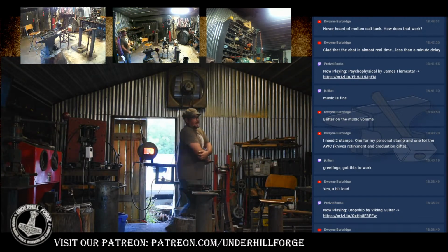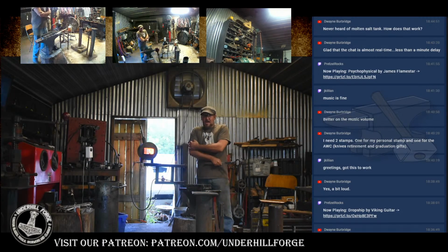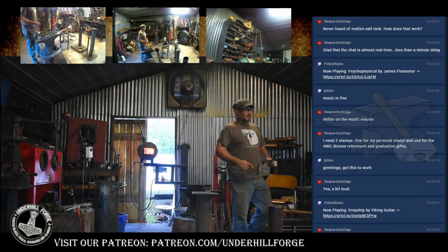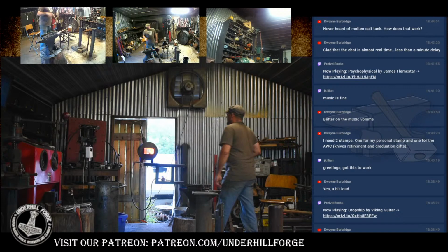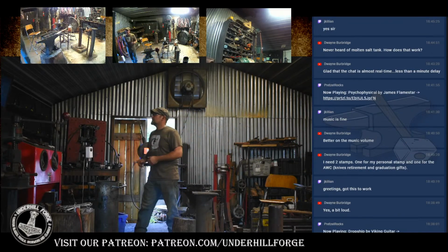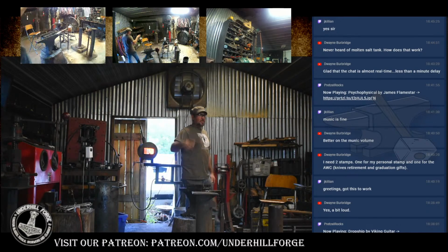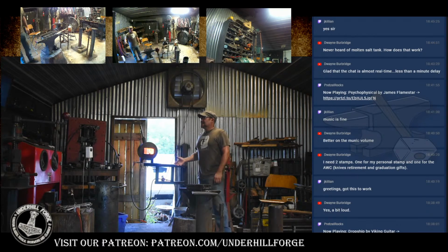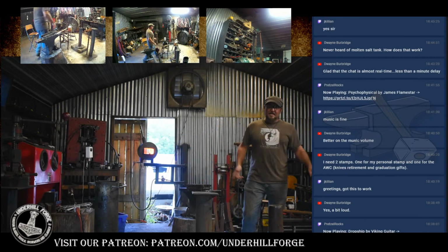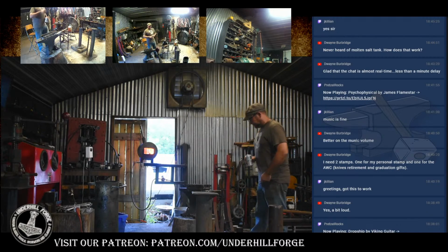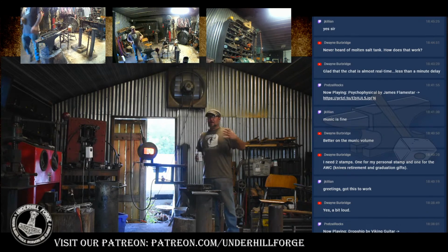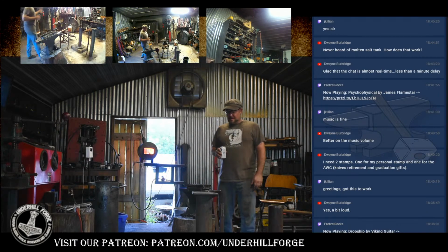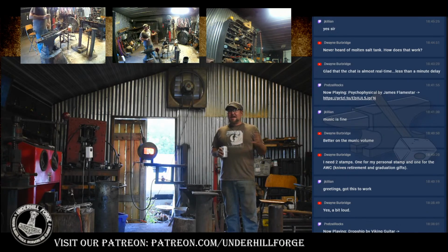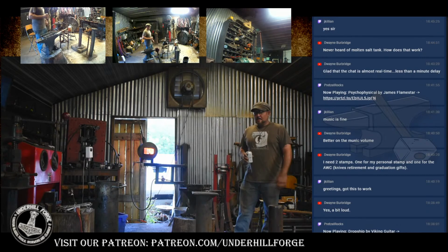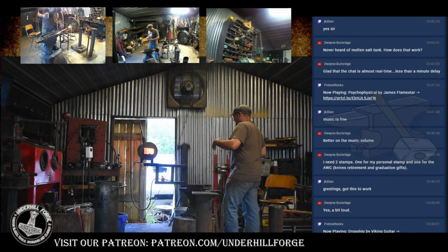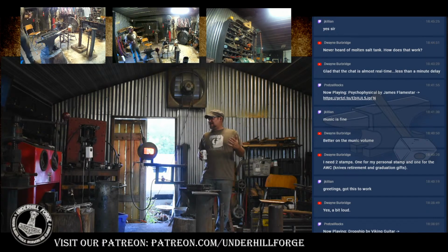So the molten salt tank is essentially a giant stainless steel tube, and the kiln is built around it. I have two different types of salts. One is what we call low temperature salt. It melts at about 430 degrees, and that's for quenching. Right now I have a high temp salt in there. I actually have two different inserts for the whole setup, because otherwise you can't get the salts out of the tube once they're cooled down. The high temp salts start melting at about 1350, I want to say.